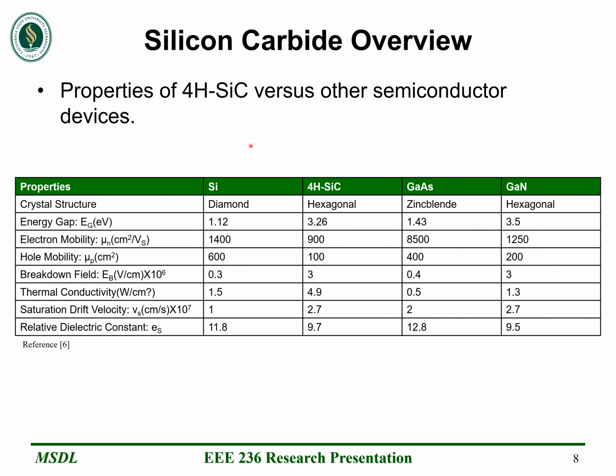So here's a table that compares some of the other different types of semiconductor materials and the properties that they possess. So let's look at silicon carbide versus silicon to start. As we talked about earlier, silicon carbide has about 3 times the band gap energy of regular silicon. However, the electron mobility and hole mobility is much less. In addition, the thermal conductivity of silicon carbide is much higher than regular silicon, which means that this is well suited for high operating environments.